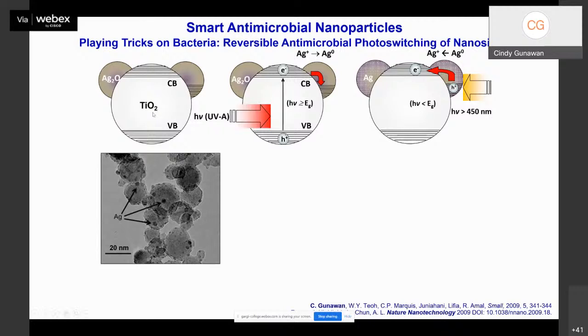To do this, we doped nano-sized silver 1 oxide on titanium dioxide. So the silver 1 oxide here is about 2 nanometers-ish. This titanium dioxide support is about 30 nanometers. And these are the electron microscopy images of these particles. You could see the big blob of titanium dioxide here and small nano-sized deposits of Ag1 on the surface of titanium dioxide.